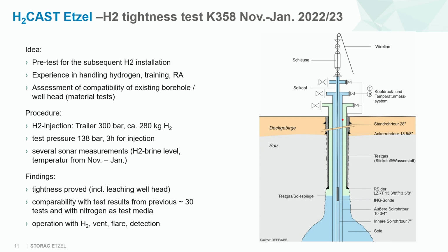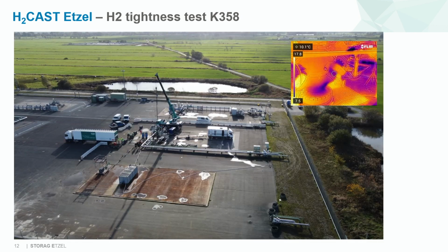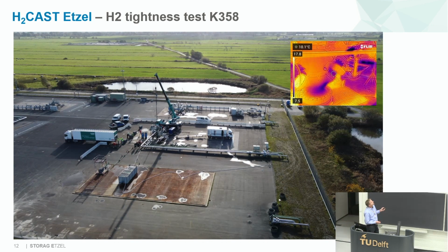And at the end of the test, we had to do some operations with H2. We had to vent and to flare the hydrogen. So this is a plot of the cavern. What we see is one of the caverns; the other one is in the background, we can't see. Here's the hydrogen truck which we had. This is Socon for the sonar control.